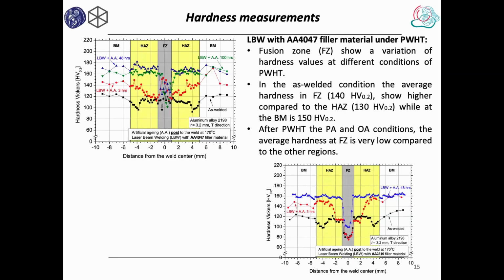With regard to micro hardness, if we deal with precipitation hardened alloys, we will always have a decrease of hardness because we introduce additional heat input during welding. And therefore, this is the question of further optimization with regard to post-weld heat treatment, how we can improve the behavior. Is it possible to increase hardness a little bit after welding? Here are the results for 4047, the high silicon content filler wire. We do not have enough flexibility here, but in case of the copper-containing 2319, we can increase hardness a little bit in the fusion zone if we apply heat treatment for 48 hours.